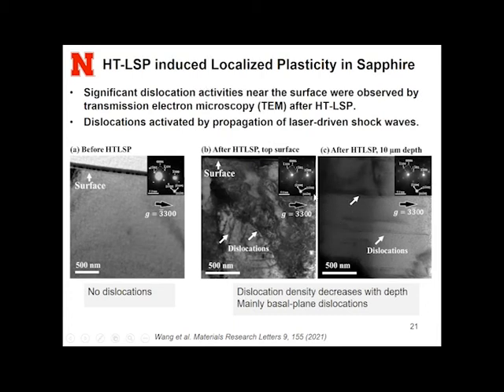By analysis of the Burgers vector and the slip plane, we found that most of them are basal plane dislocations. Basal plane dislocation is consistent with the deformation mechanism of single crystal sapphire, in which the main slip system is the basal plane at high temperature for alumina. We think the dislocation here is activated by the laser-driven shock wave. One evidence here is the shock wave decreases with depth, and the dislocation density also decreases with depth.